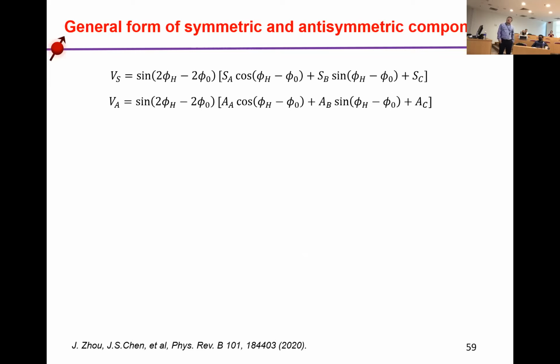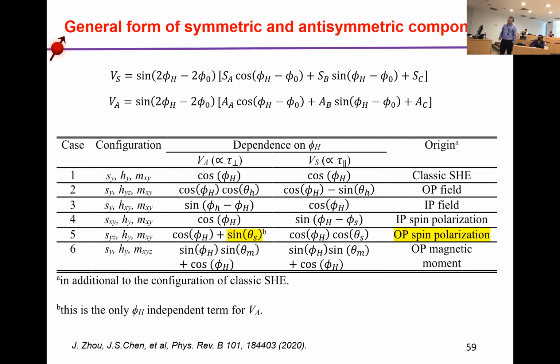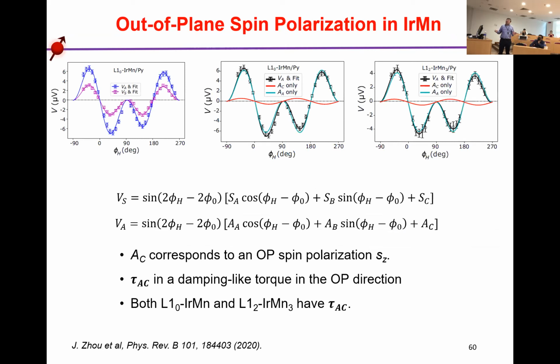So based on this, we have derived this VS and the VA. VS is the symmetric component. VA is the asymmetric component. The first term refers to the AMR effect. For the rest, the different components have different origins. Here we summarize. Now we only consider the fifth. It's due to out-of-plane spin polarization. That means as long as there is some constant component, we see there is an out-of-plane spin polarization. So we use this method. We really have demonstrated there is an AC component which corresponds to the out-of-plane spin polarization.